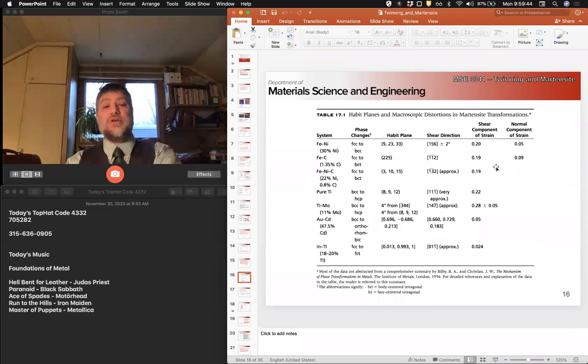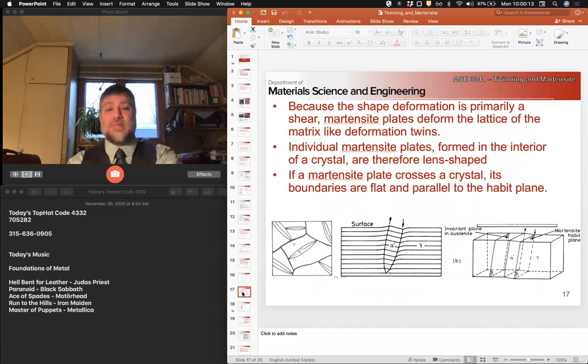And what's the volumetric component? In this case, the change in our lattice parameters when I go from FCC to BCT is close to 10%. So my overall strain in my system from Martensite becomes very large. And yes, it does actually form a chain reaction. I'll talk about that in just a bit. Okay?